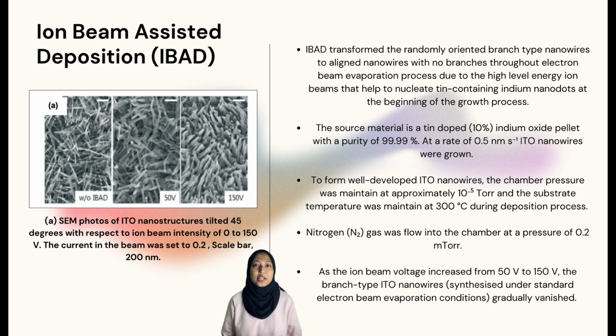IBAD transformed the randomly oriented branch-type nanowires into aligned nanowires with no branches throughout the electron beam evaporation process, due to the high-energy ion beams that help to nucleate tin-containing indium nanodots at the beginning of the growth process. The source material is a tin-doped indium oxide pellet with a purity of 99.99%. We can see that at a rate of 0.5 nanometers per second, ITO nanowires were grown.